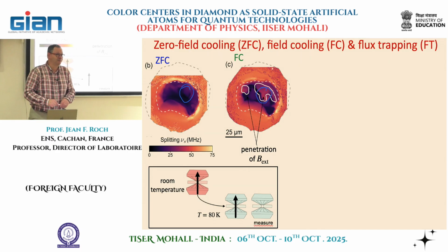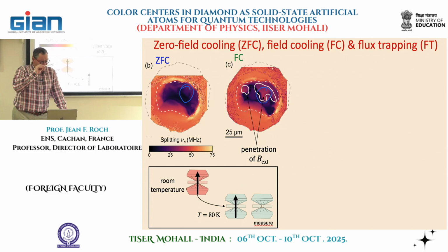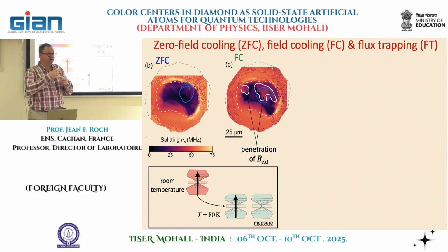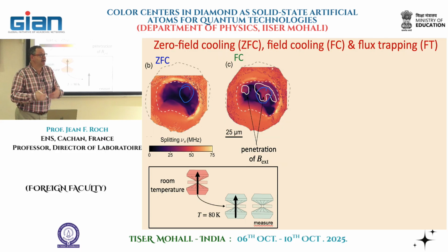And this is perhaps a very beautiful experiment, in that we apply a magnetic field when we cool down the system, like before, but instead of heating the sample with the magnetic field still on, we remove the magnetic field. Now we have launched some superconducting current inside the sample, and those superconducting currents can survive almost forever. This experiment says that a superconducting current launched in a superconductor can stay there for years. So this is what we have done. Somehow we remove the field and we try to see what happens.